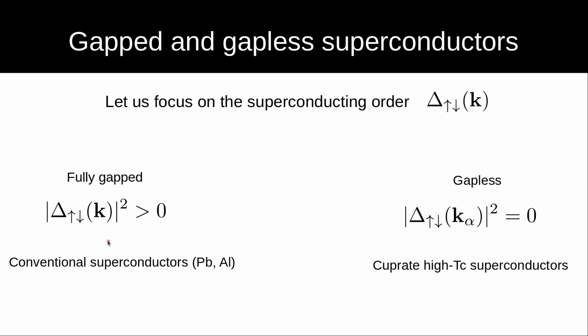But then there's an unconventional superconducting state that is a singlet, which is the so-called gapless superconducting state, and in particular a state where instead of having an S-wave pattern in reciprocal space, we have a D-wave pattern. So a pattern with L equal to 2 in reciprocal space. And this is the case of cuprate high temperature superconductors. So many of the superconductors that show critical temperatures on the order of hundreds of Kelvin are spin singlet superconductors, but not S-wave superconductors. They are D-wave superconductors. They are gapless, and the gap closes at some points of the Brillouin zone.